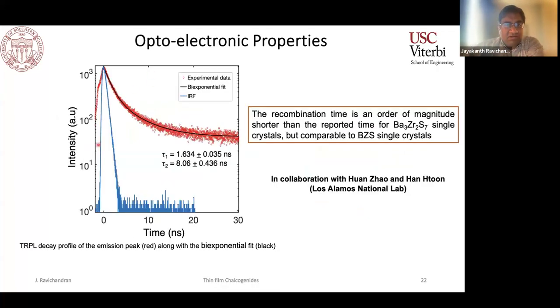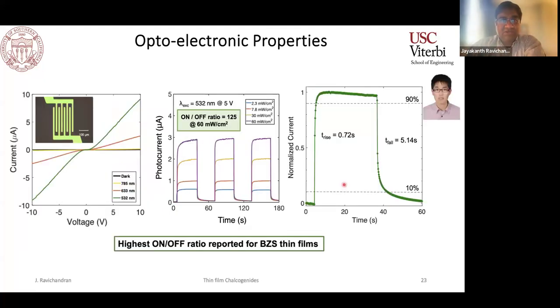We also studied its optoelectronic properties using time-resolved PL. The numbers were really similar to what we got for our single crystal, suggesting that even though it tends to be polycrystalline, the overall quality is comparable to what you would get in high-quality bulk materials. This is work that was done in collaboration with Huan Zhao and Han Htoon at Los Alamos National Lab. Huan has moved on to Oak Ridge now for his current position.